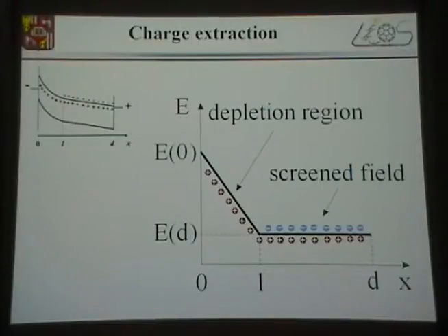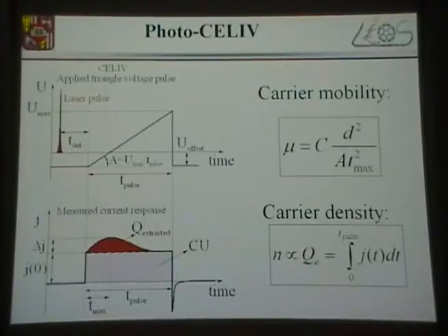So those are the dopants, immobile dopants, and those are the mobile electrons. And you see this is the electric field that's dropping in the film. So this you can think of like a Schottky barrier. And the electrons move right, they're escaping to the electrode. Therefore, the new electrons are not injected, so d is the film thickness. New electrons are not injected because the contact is blocking, those are going away, and by measuring the time required for the electrons to go through the film, we know the film thickness, we calculate the velocity, we know the velocity, we know the mobility. So you see the method is very, very simple.